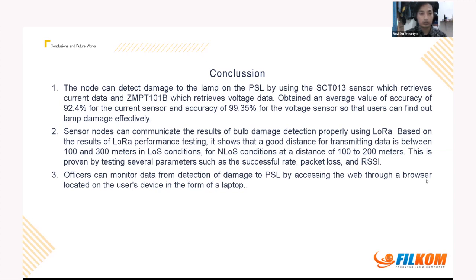Number 2, the sensor node can communicate the result of bulb damage detection properly using LoRa. Based on the results of LoRa performance testing, it shows that a good distance for transmitting data is between 100 and 300 meters in LoS condition, and in NLoS condition at a distance of 100 to 200 meters. This is proven by testing several parameters such as the success rate, packet loss, and RSSI.